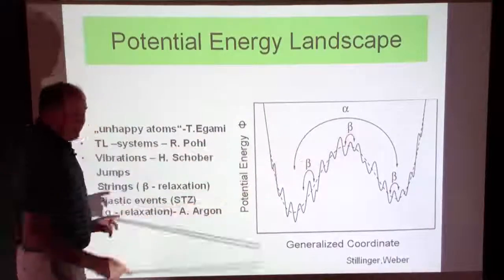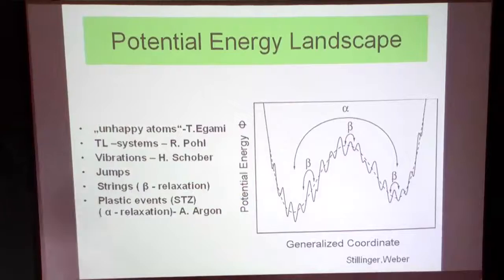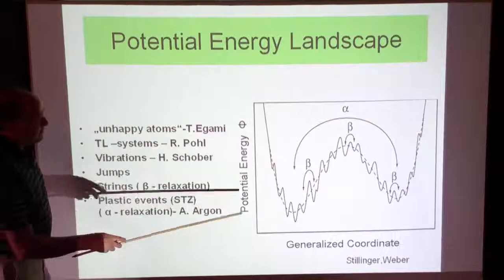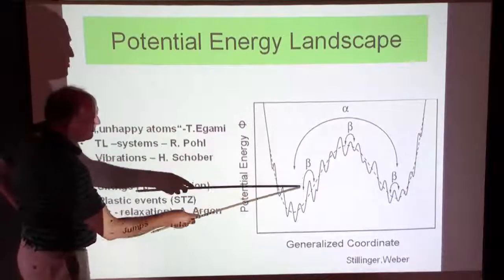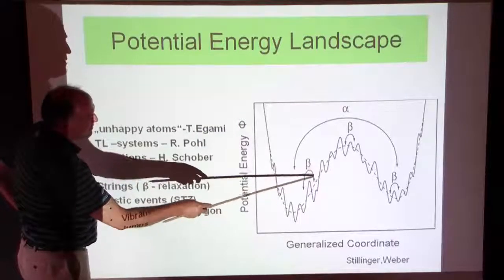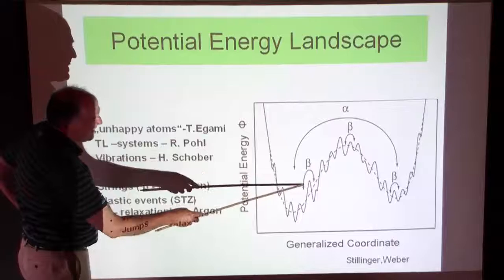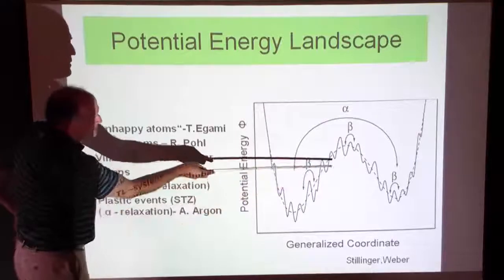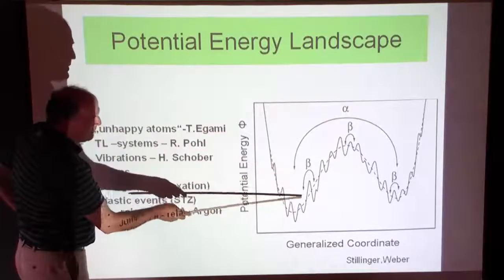But we need a second effect, which is diffusion below Tg, relaxation, aging, rejuvenation, and all these things which we also discussed briefly during the conference in the last 2-3 weeks here, which needs a secondary excitation, and this is this slow beta process, which is inside one meta-basin, reversible. You can go up and down again.